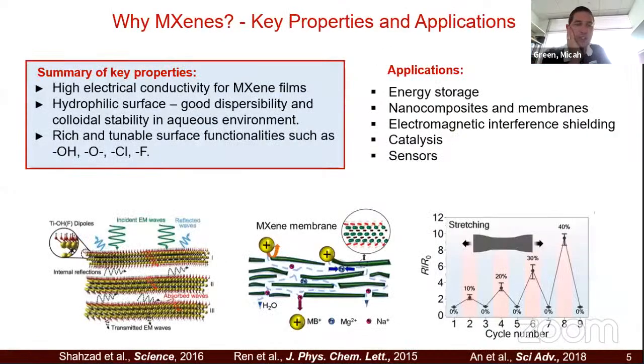So I mentioned that these things are electrically conductive. That's exciting. They have hydrophilic surface groups, which means you can disperse them in water and process them as films. And we've done a lot of layer by layer work here at Texas A&M. And you can even tune what those surface functionalities are in order to get them to interact with an outside surface. And if you just do a quick search on applications of these materials, there's a lot in the battery realm in terms of energy storage, supercapacitors, a lot with nanocomposites, EMI shielding, and then more recently, even catalysis and sensors.